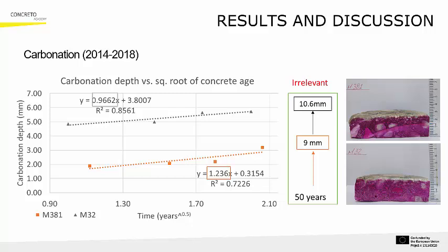However, as expected, the carbonation rate is higher for LC3. This is attributed to its lower buffering capacity, resulting from the high clinker replacement rate and the significant consumption of portlandite in the synergistic reactions previously presented. When projected to 50 years, the predicted carbonation depth remains insignificant for the durability of these reinforced concrete elements.